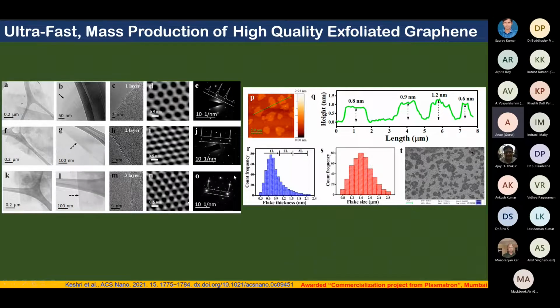Now in image R, you can see the flake thickness and the count frequency. We analyzed around 300 to 400 flakes, and we found that most of the flakes are less than 0.9 nanometer, and then you can see the second layer and the third layer. From this frequency chart, we concluded that out of 400, more than 330 flakes were around 0.9 nanometer. That is why we reported 85% single layer. Now the lateral flake size ranges from 0.8 to 2.8 micron.